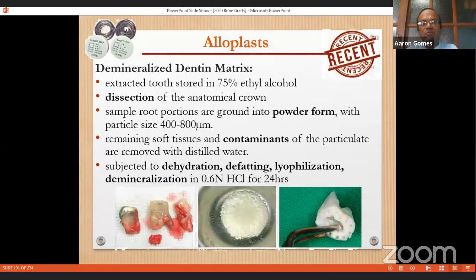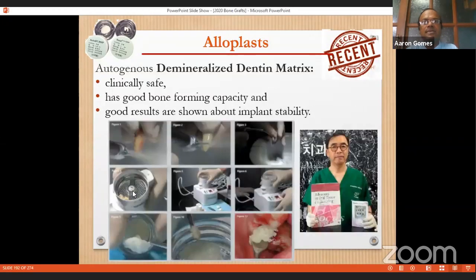So the extracted tooth is stored in 75% ethyl alcohol. The periodontal ligament area is cleaned of all the soft tissue remnants. The dissection of the anatomical crown is done. It is ground into a powder form of 400 to 800 microns. Contaminants are cleaned with distilled water, and it is subjected to dehydration, defatting, and lyophilization, as well as demineralization in 0.6 normal hydrochloric acid. This is how it is made.